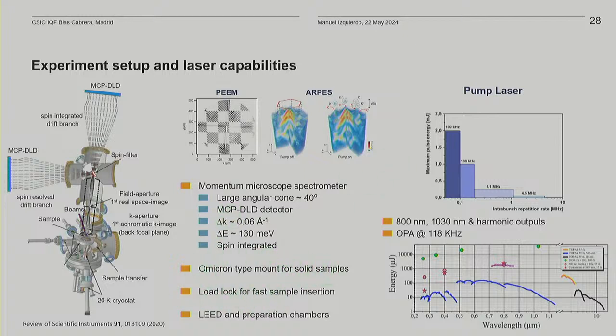In order to do pump-probe experiments, what we have is the PP laser provided by the European XFEL. It can run between 100 kilohertz and 4.5 megahertz. It has two outputs, one at 800 nanometers and the other at 1030. And then you can also do second and third harmonic. And then there is the possibility of extending the wavelength range by using an optical parametric amplifier. Right now it's running at 118 kilohertz, at least in SASE3.